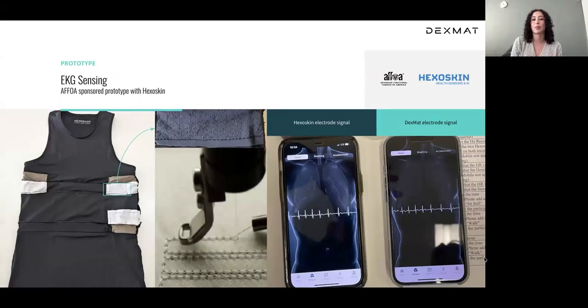So I'm going to cover some of the prototypes that we've developed at DexMat. This one was actually through a project that was sponsored by AFFOA in partnership with a company called Hexoskin. They make EKG vests and t-shirts, and they typically use these silver-coated fabrics that after multiple washes start to oxidize and you get a degradation in the EKG signal. So the goal of the project was to assess whether Galvorn-based electrodes would have comparable performance in terms of EKG signal while also having that washing durability. And by the end of the project, we were able to prove that it does indeed provide reliable EKG signal while also holding up to multiple wash cycles without a degradation in performance.